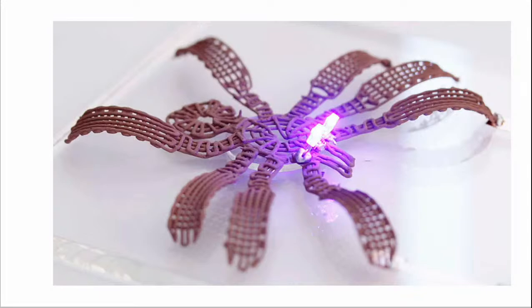It's a conductive gel. What they do is a one-step, room temperature 3D printing of metallic objects using a gel. They suspend micron-sized copper particles in an indium gallium alloy, which is everyone's favorite low-temp experimental metal. They then mix it, and it forms a kind of gel network. They then extrude this using a conventional syringe extrusion type system. Then it dries and leaves behind the part.